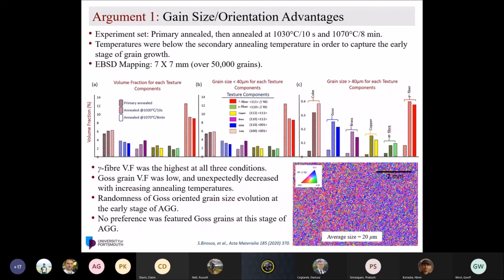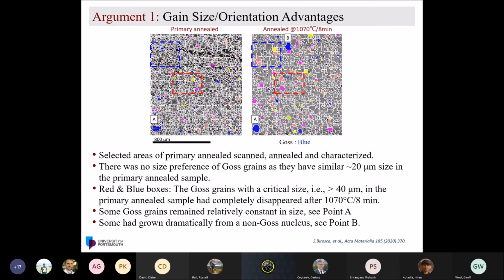So we had all the grain size data, and we looked at the histogram of it, and we separated the two main grain size humps, or peaks. We found that 40 micrometers is a stage where the grains have grown more than normal, because the primary anneal grain size was 20 micrometers, right? So anything above 40 we counted as a later stage of abnormal grain growth. We separated this to understand it even further, and we got the same conclusion. We didn't find much difference for anything below that, and so on.